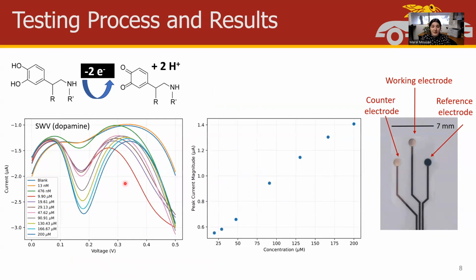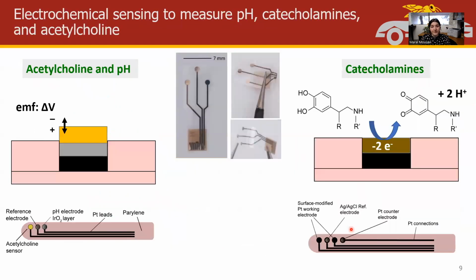The peak height, or the peak current value, will correspond to the concentration of these catecholamines, and that's the additional information that we can get in order to quantify the levels. So this plot here shows you the linear correlation between peak current magnitude and concentration of dopamine, and we see similar behavior for the rest of the catecholamines.